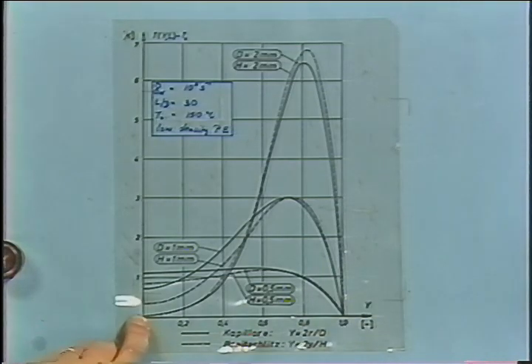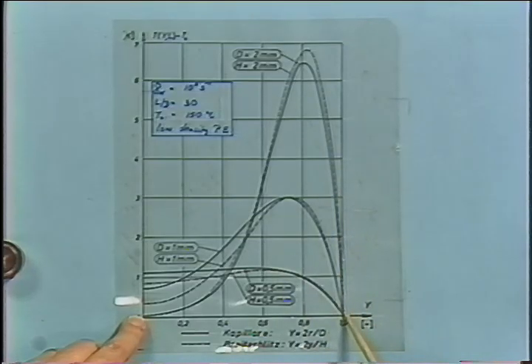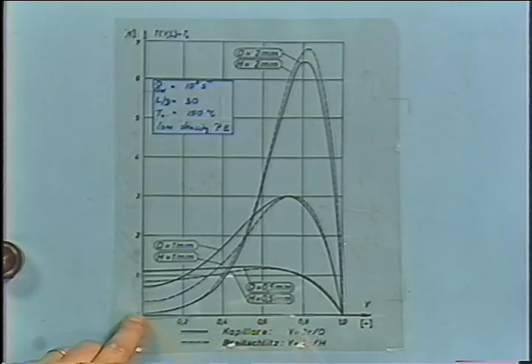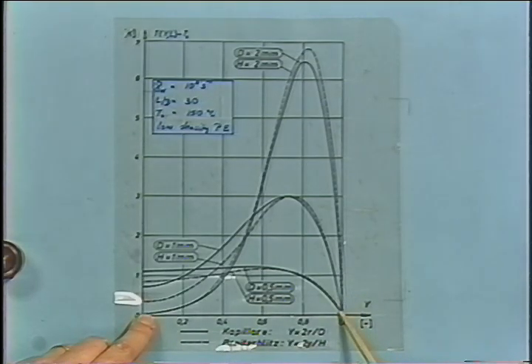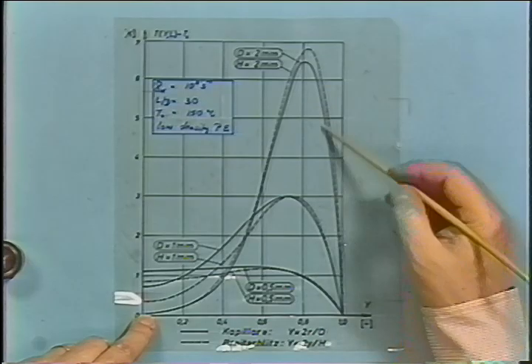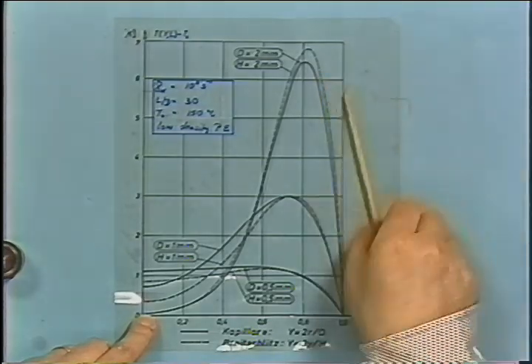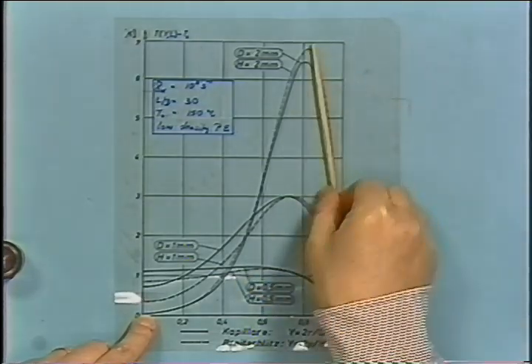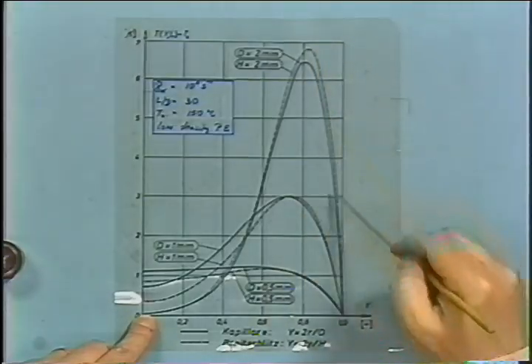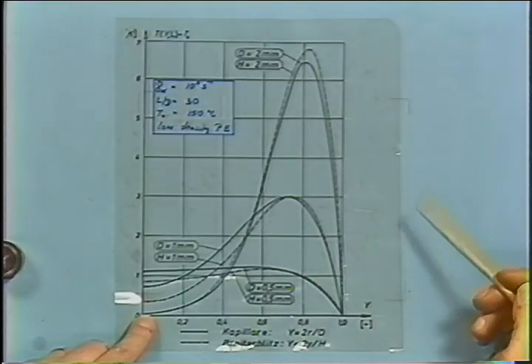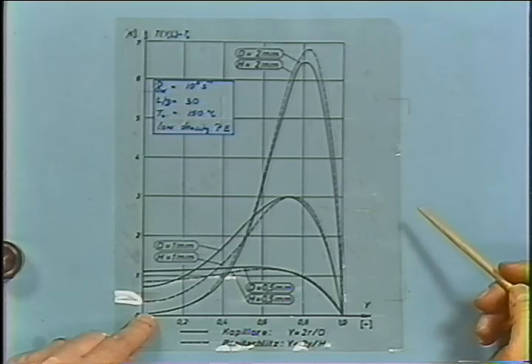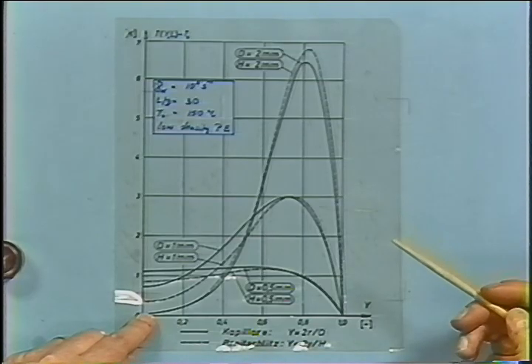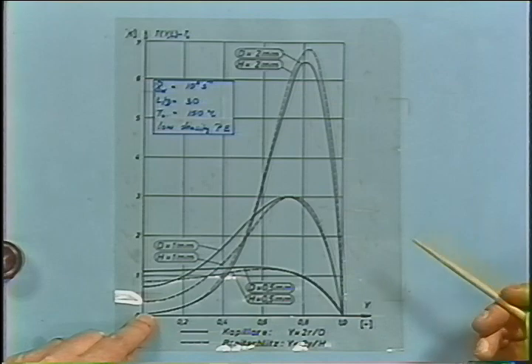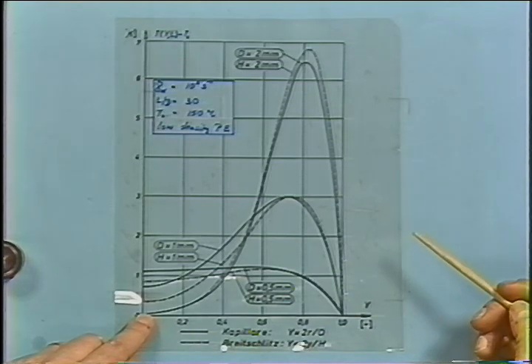This is the center of the capillary. This is the wall of this capillary. So near the wall, the viscous dissipation is highest because shear stress and shear rates are high, and it's 0 in the center. Now, near the wall is also the isothermal wall condition, which gives rise to conduction. So near the wall, as the temperature increases, there will be a gradient to the wall, and there will be a flux introduced into the wall. This will cause difficulties for maintaining constant temperature conditions in this experiment.